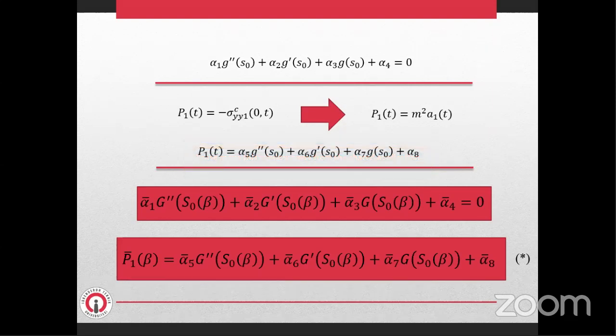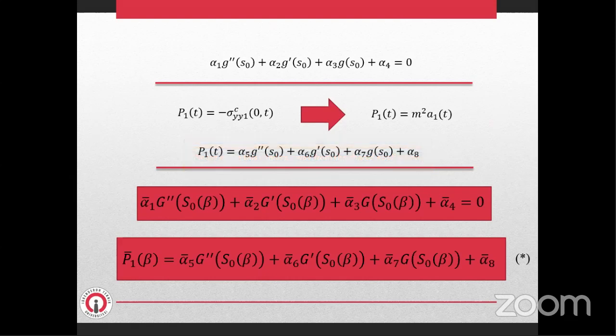The stress fields and contact pressure are separated into two parts, zeroth and first order quantities, by using a similar procedure as in the thermal problem. Similarly, the mechanical boundary conditions are separated by using a Taylor series expansion in the vicinity of the zeroth order quantities. At the end of the determination of stress fields in each layer, we obtain a two-dimensional differential equation with variable coefficients which include the residual stress function and its derivatives with respect to the mean shell thickness. When the problem wherein the thermal and mechanical fields are uncoupled along the mold-casting interface, as in the present model, has been examined, efforts have focused on the development of the contact pressure perturbation. The zeroth order contact pressure is always equal to the hydrostatic pressure, and it is constant during the process. For this reason, the first order part of the contact pressure is more important for investigating groove instability.